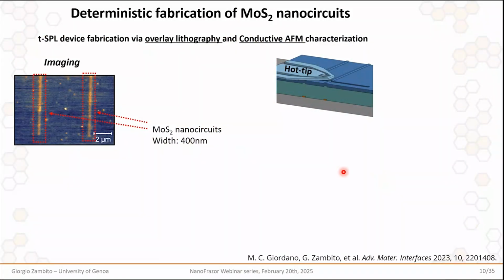So since this is a NanoFrazor webinar, I think it's also interesting to stress another capability given by this kind of technique, which is the overlay lithography. So basically, the idea is that we can exploit the same tip that we use for lithography, but in a colder configuration, so without inducing any patterning on the polymer layers, to detect underlying objects, such as these two MoS2 nanofingers that we previously fabricated, as previously discussed.